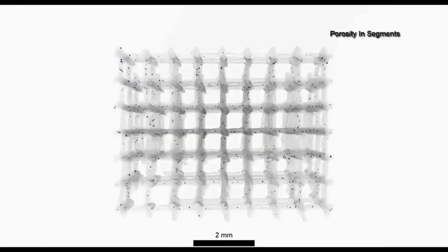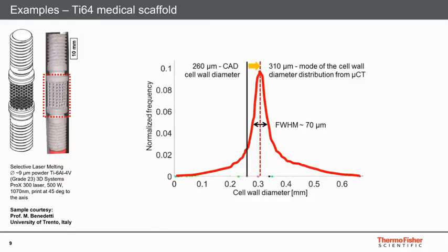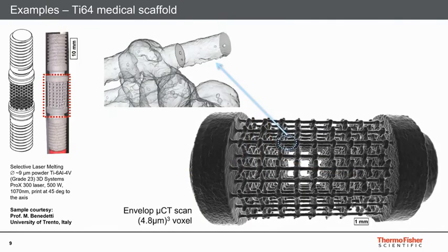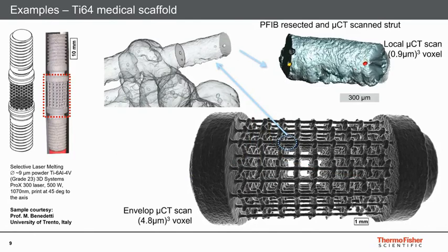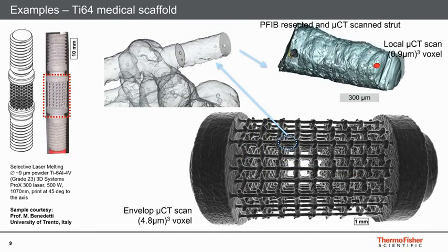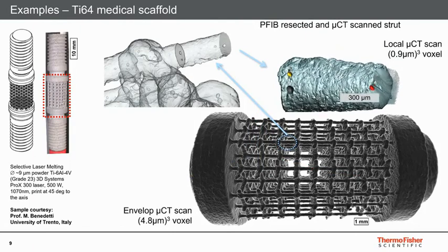On average, the struts are thicker than the designed ones, and we see small struts being weak spots of the build. From the full sample scan, we found a location on a strut having pores in it. We resected the strut using PFIB and we mounted it on a holder to do a high-resolution CT study.